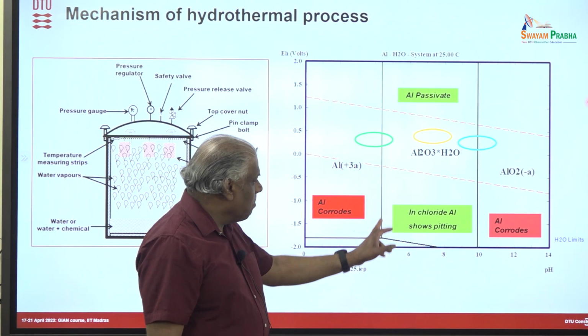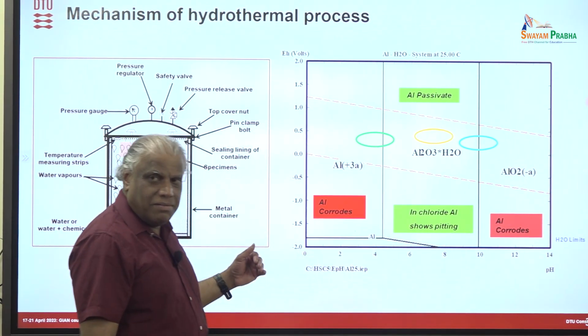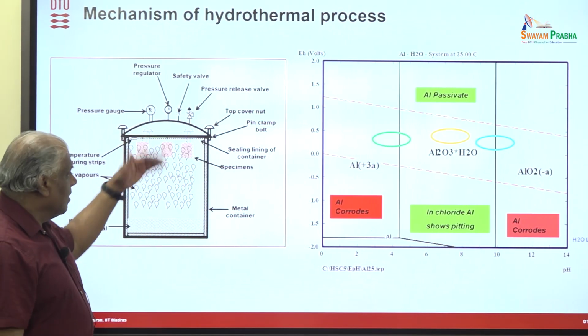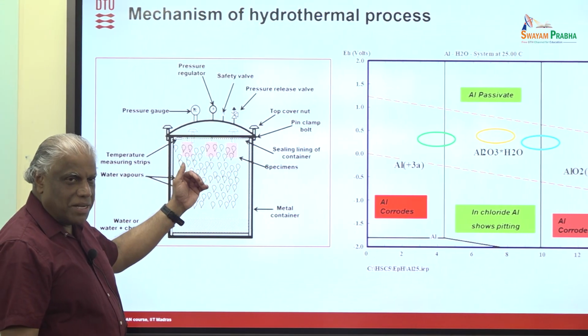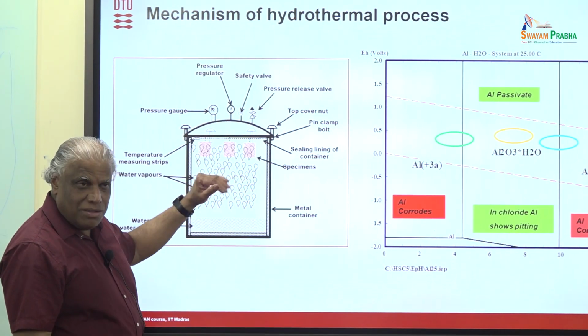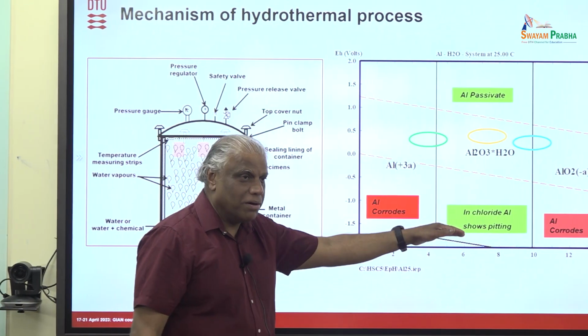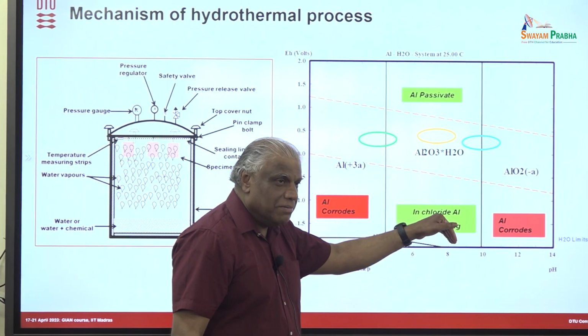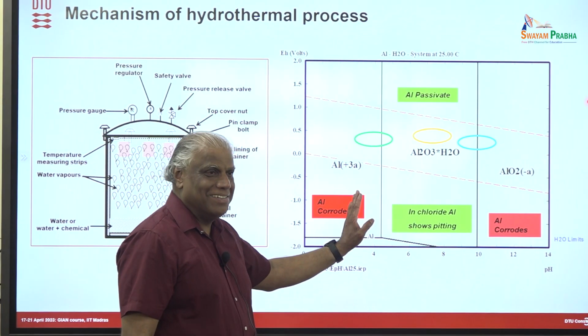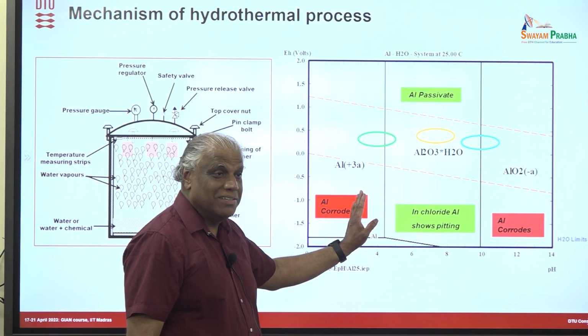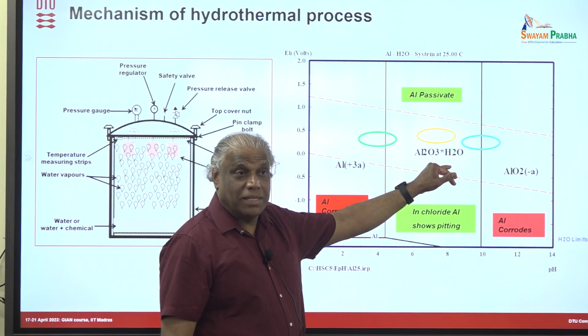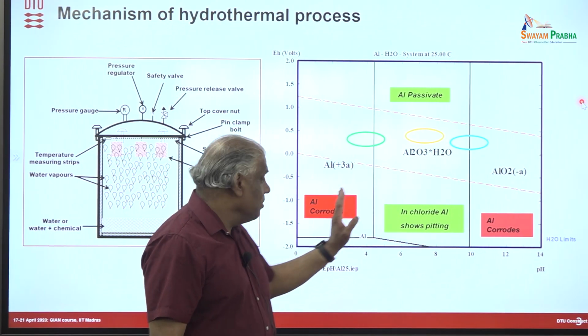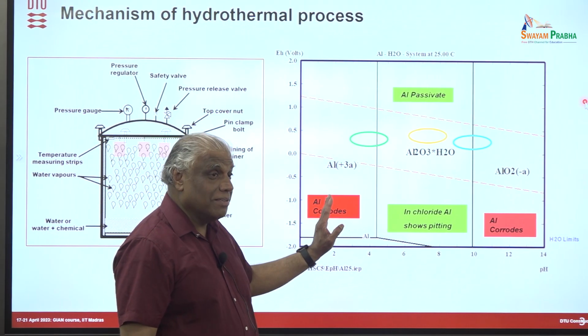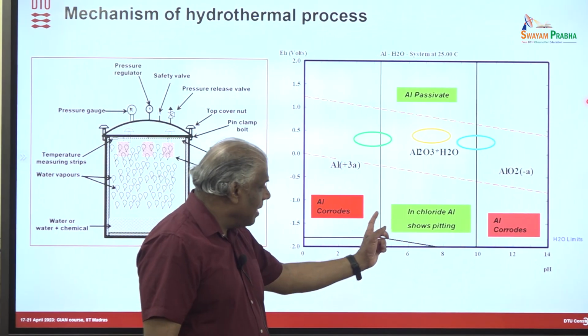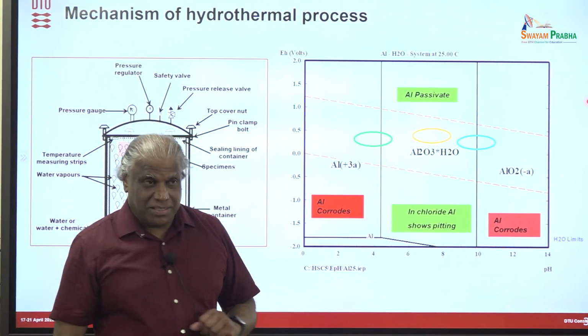And then what happens is that you are playing with this boundary. When the acidic solution is there, when the steam is more or less produced and a little bit of a spray, you have that acidic solution which will make the aluminum dissolve more. When the aluminum is dissolving, this boundary is shifting here because of the higher concentration of aluminum on the surface. Immediately that aluminum will be precipitated as aluminum oxide. So we are playing with this boundary. If you use too much acid solution, you don't get this coating because then the aluminum will be dissolved. You need to play around this region to get the best coating. So that's the mechanism by which we work in this.